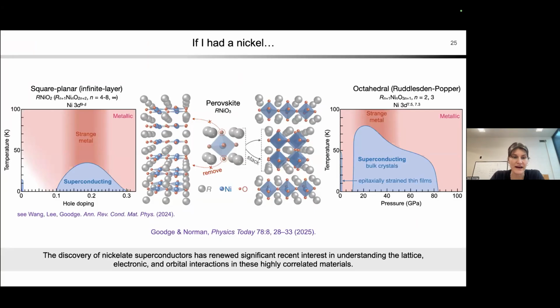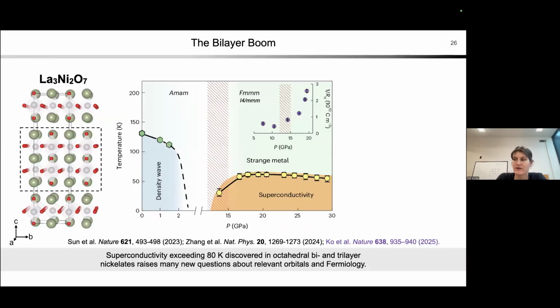Okay, so just to come ahead a little bit more, I told you about these nickelate superconductors over here on the left, but I showed you on the early plot, there's actually a new family of nickelate superconductors which have emerged more recently. They're sort of related in their structures. You can see that one of them is missing oxygens and one of them has this layered stacking. And we're still trying to figure out exactly how these materials relate to each other. But we've also started looking at the ones, what we call Ruddlesden-Popper materials over here on the right. So these, unlike the other nickelates, were actually more of a surprise to the field. They weren't initially predicted. They came out of nowhere. And now we're trying to figure out what's going on.